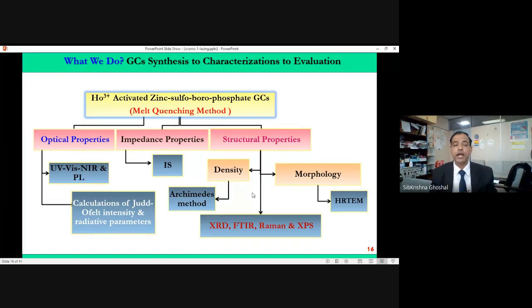Then we have to do a lot of structural and morphology characterization, such as XRD, X-ray photoelectron spectroscopy, XPS, Raman spectroscopy, FTIR, Fourier transform infrared spectroscopy. Then we also do TEM, transmission electron microscopy, high resolution transmission electron microscopy, FESEM. All these are for the morphology characterization. So the complete characterization results of structural, morphological, impedance or dielectric properties, optical properties, then monochromaticity properties by the CIE chromaticity diagram. We have to do all this to understand the properties.